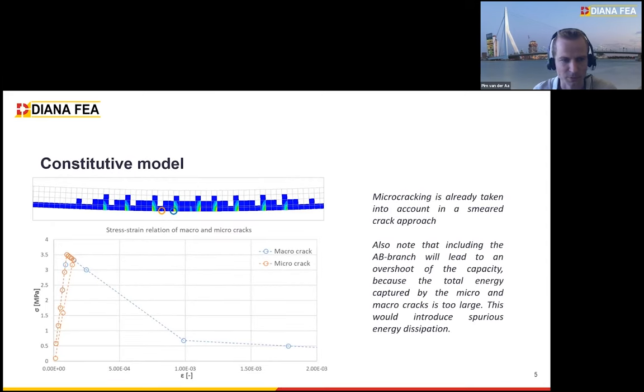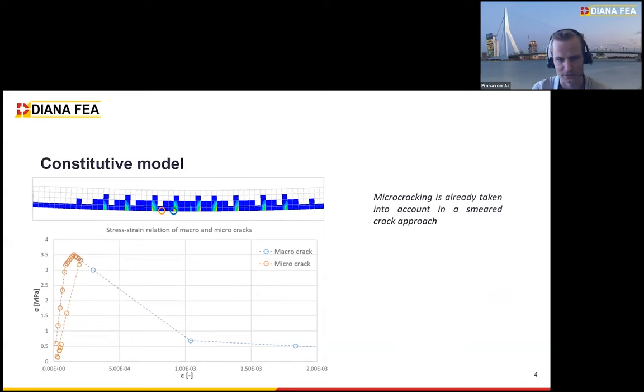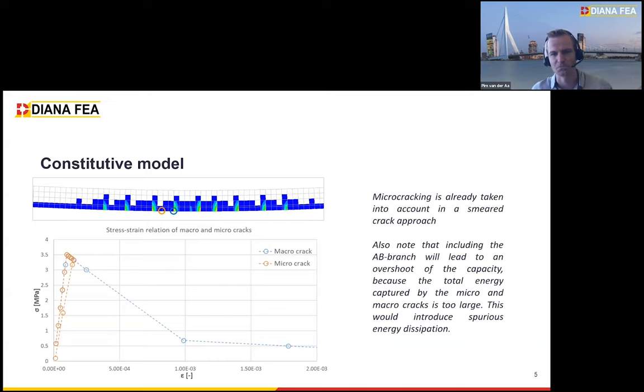I also did it without the small part, and then you see that it nicely introduces the micro cracking, which is the orange line. You can see it goes up to the peak, small softening, and then it starts unloading. That's typically what we see with micro cracking. So it's good to note that you should not use the stress strain diagram in the previous slide, because you actually introduce extra energy. The energy dissipation in the previous slide is higher than the energy dissipation in this slide. That means that if you use that stress strain relation, you're actually overshooting your capacity. So that's why we recommend, for the smeared crack approach, not to use that pre-peak branch.